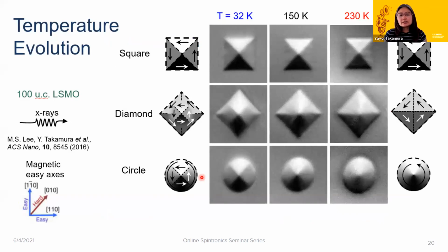But again, these complex oxides always give us some interesting things. If we now take the same sample, the data that I just showed you is on the right-hand side, 230 Kelvin, purely in the Landau structures for all of the samples. But now if we cool it down to cryogenic temperatures, and again, not super cold, one thing you can see is that for the square, the edges along the easy axis of the material, nothing happens. Maybe the images get crisper,